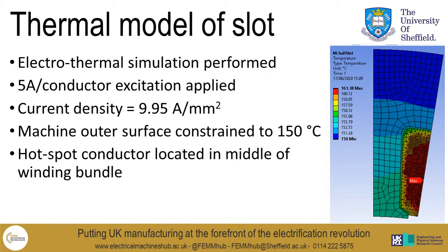So the first use of this model is to determine the location of the hotspots within the winding. To achieve this, we used an electrothermal simulation whereby 5 amps was applied to each of the conductors, which equates to a current density of 9.95 amps per millimeter squared. The machine outer surface was also constrained to 150 degrees to model the cooling of the machine. You can see from this slide the location of the hotspot, which is in the middle of the winding bundle, which makes this the conductor we're most interested in determining the stress of.